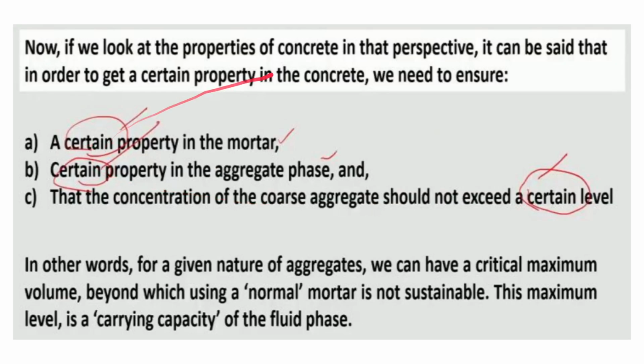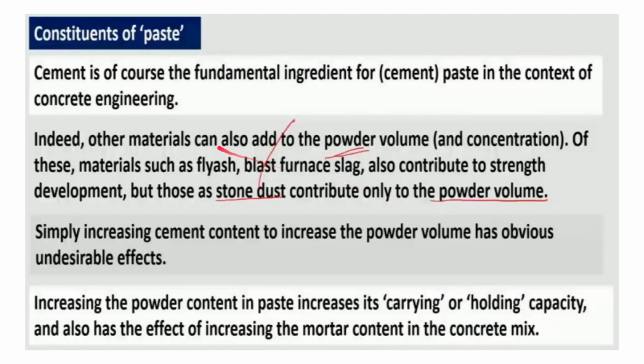That's why the properties of concrete matter a lot. Basically the property of mortar, property of aggregate phase, and the concentration of coarse aggregate should not exceed a certain level when flowing through a pipe. That value of maximum level of coarse aggregate is basically called the carrying capacity of the fluid phase. So that is the critical maximum volume beyond which a normal mortar is not sustainable. So we have to take into account all these factors.